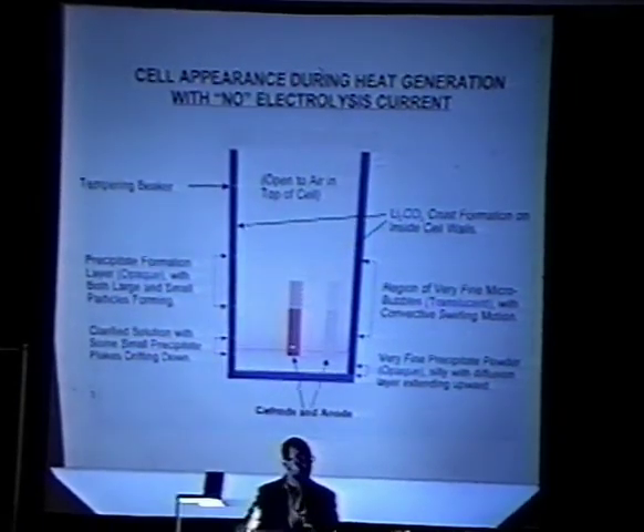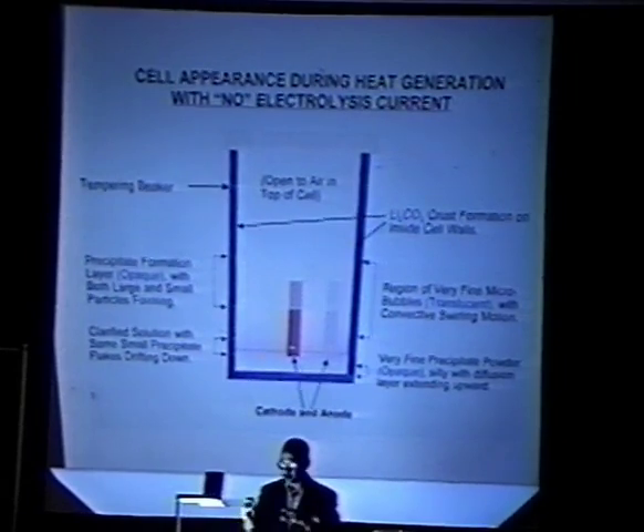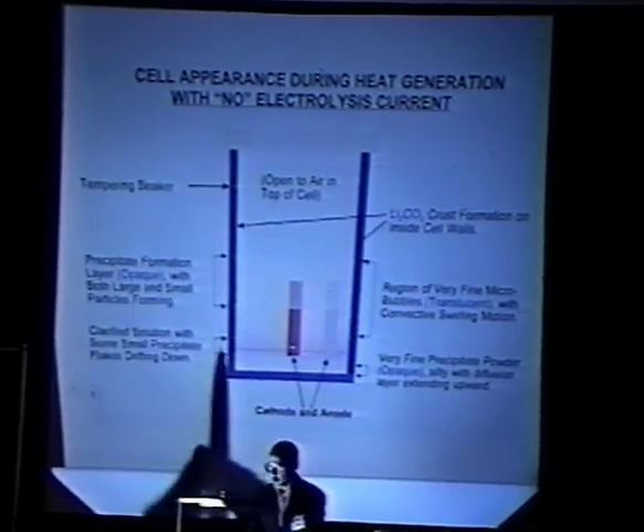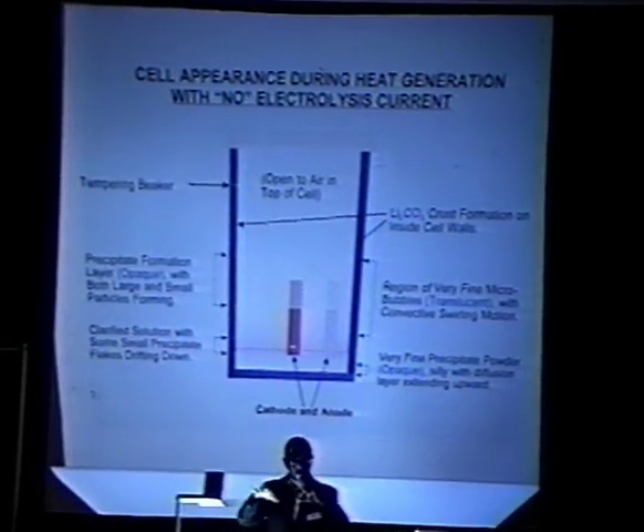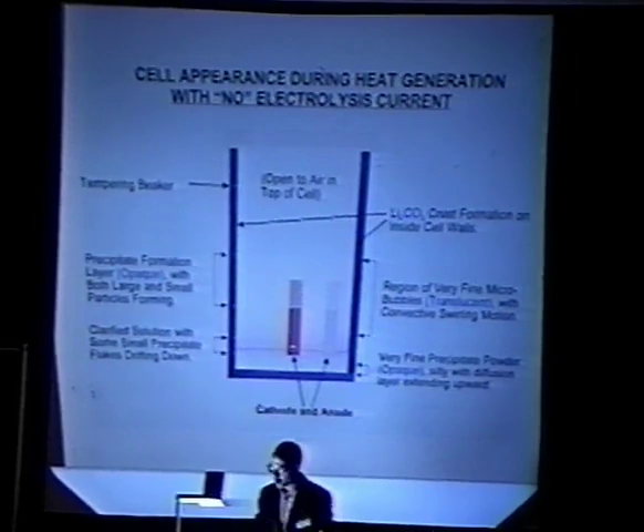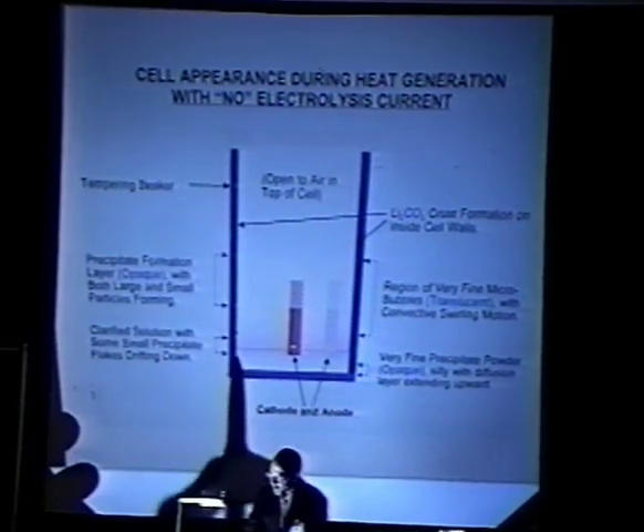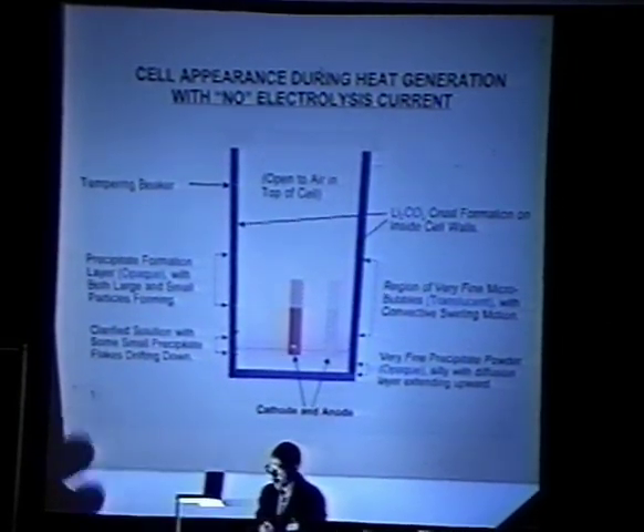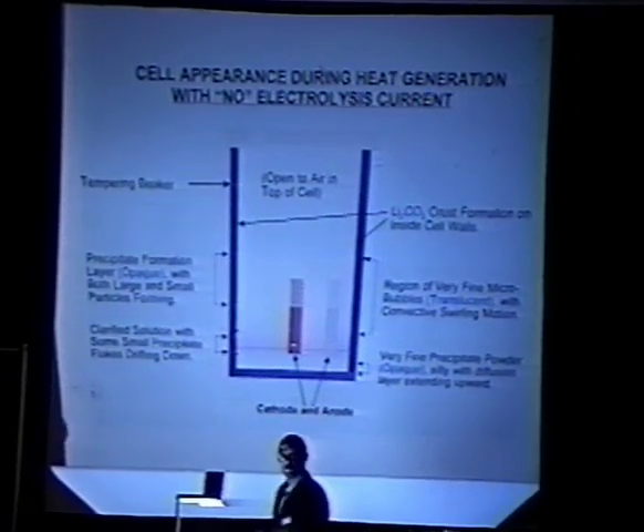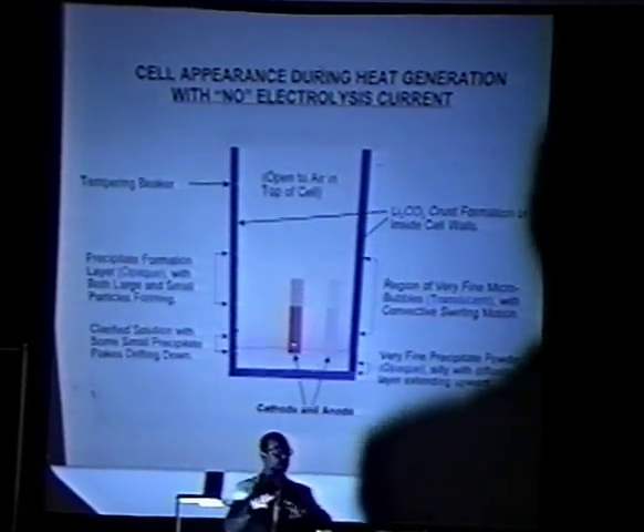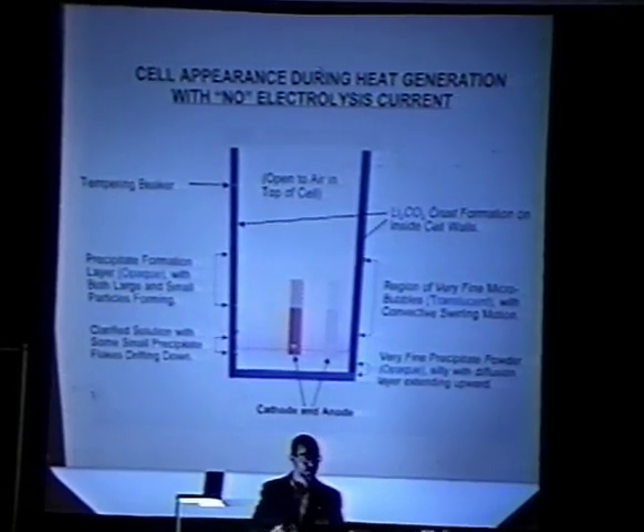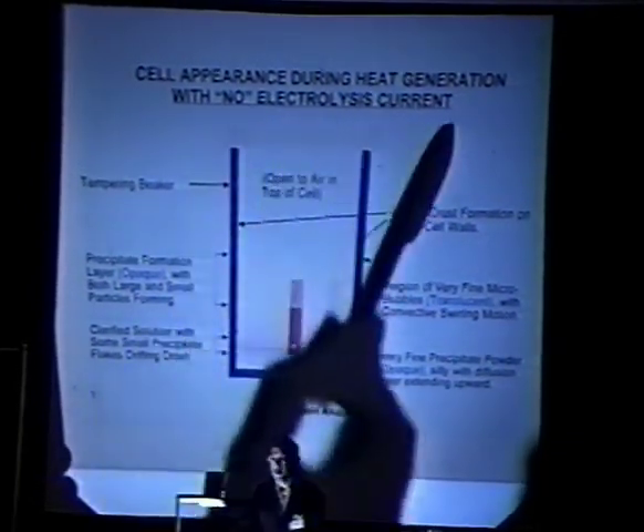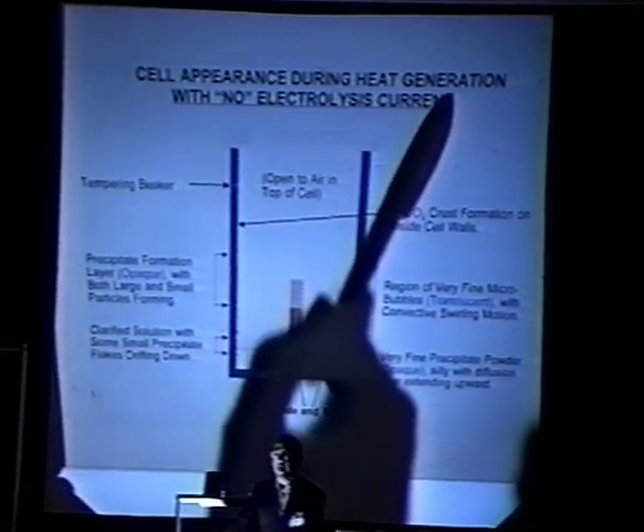You can actually see these large and small flakes of precipitate forming, and they begin to diffuse and fall down. And they are opaque. It makes it where you can barely see through the solution, and these do form and tend to swirl, and gravity tends to make them come on down to the bottom. There's a region right in here that I call the clarified solution, and it has very small precipitate flakes drifting down through that, and that's different from the electrolysis one I'll show you in just a minute. Again, this is one with no electrolysis current. There are hours and hours of this thing producing heat, looking just like this.